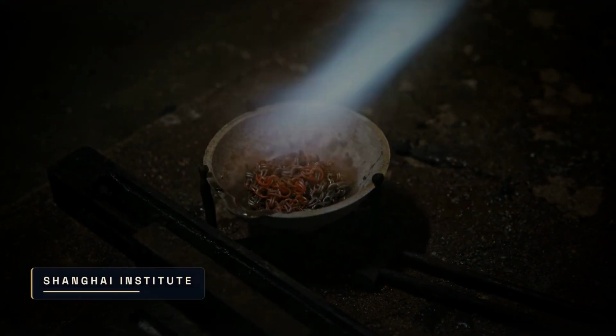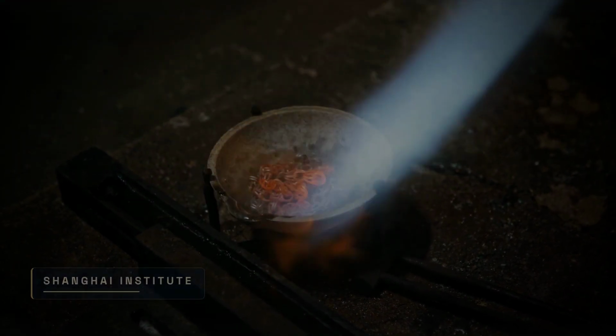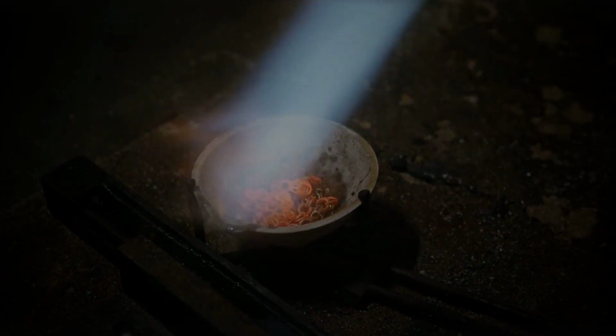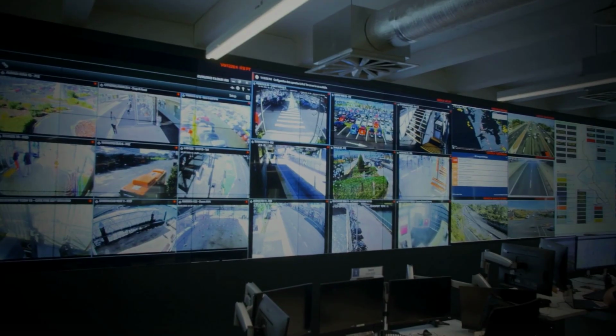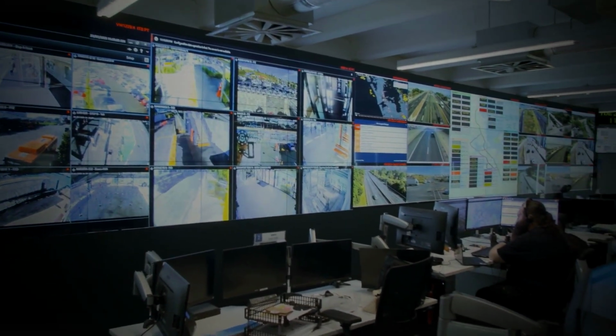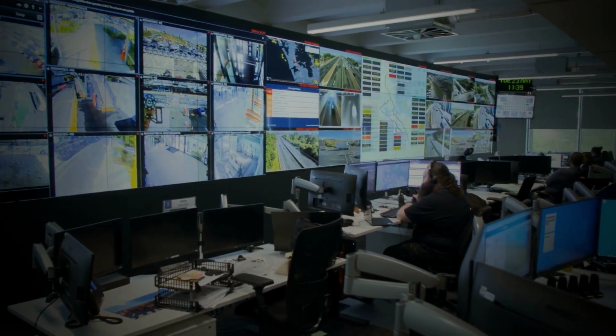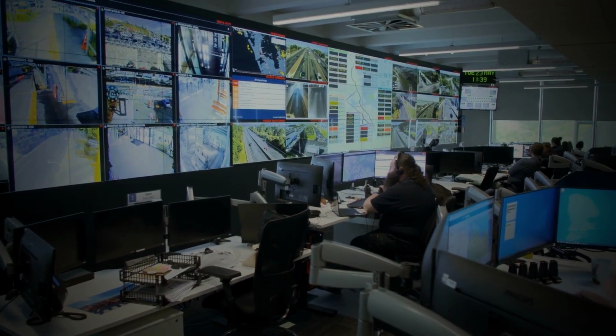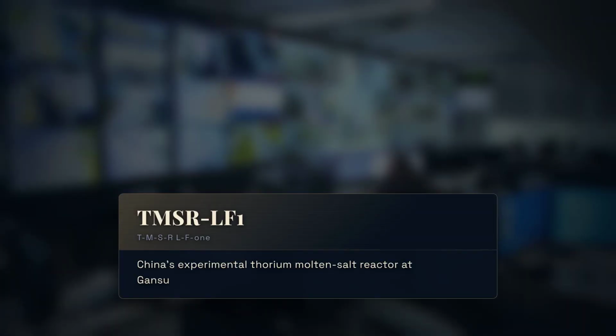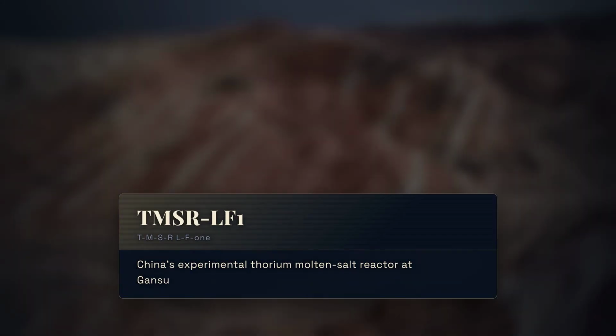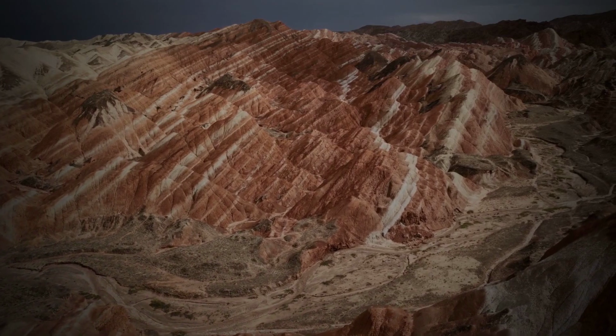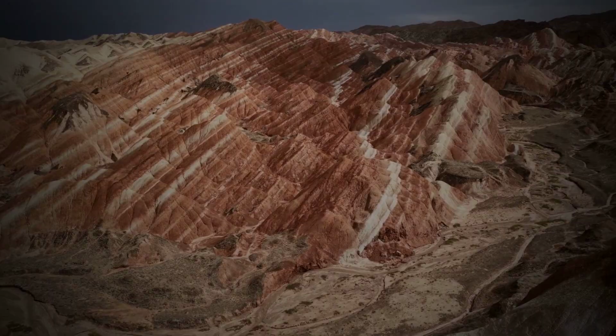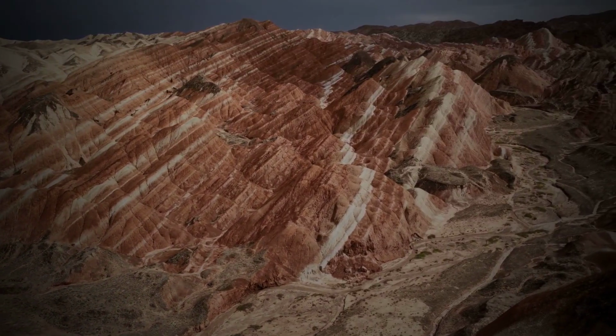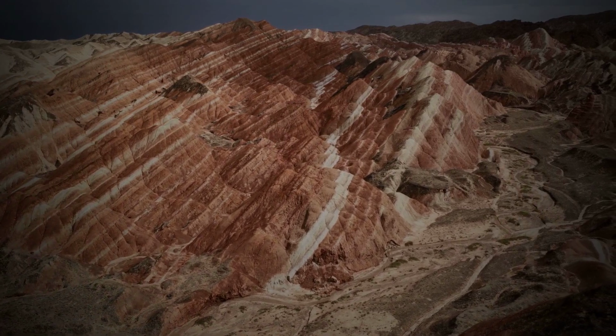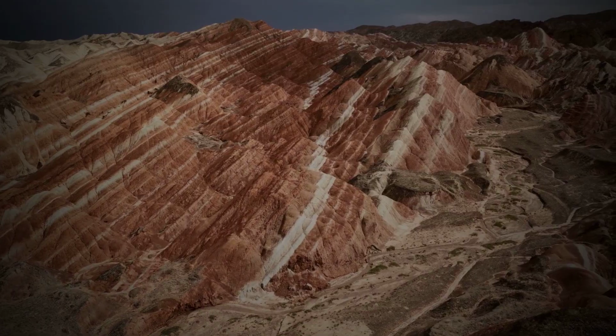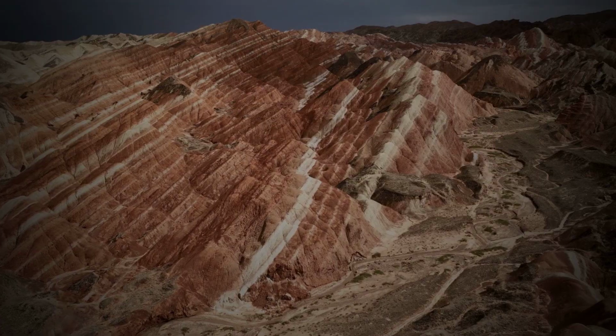At the Shanghai Institute of Applied Physics, metallurgists have developed modified nickel alloys with adjusted chromium and molybdenum content, aiming to resist tellurium infiltration better than the original Hastelloy N formulation. The TMSR LF1 also carries online chemical monitoring equipment that samples the salt continuously, tracking oxidation states and impurity levels in real time, so operators can adjust conditions before corrosion accelerates, a capability Oak Ridge's team never had access to in the 1960s.